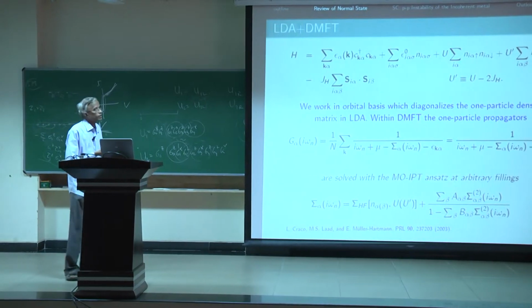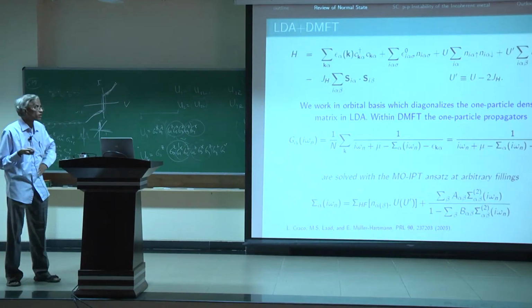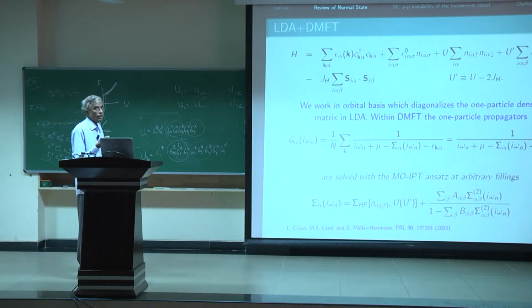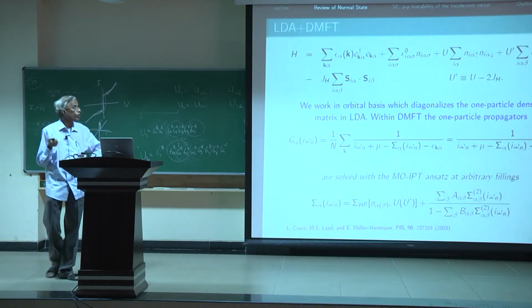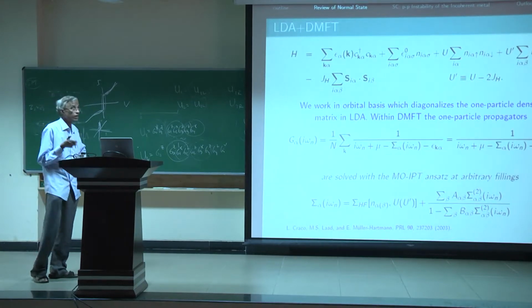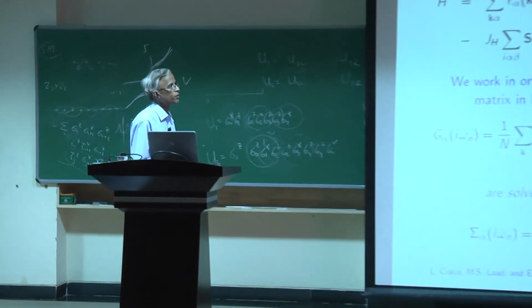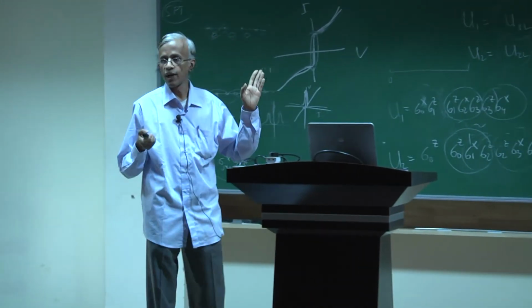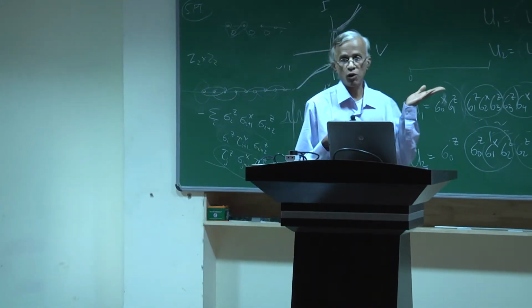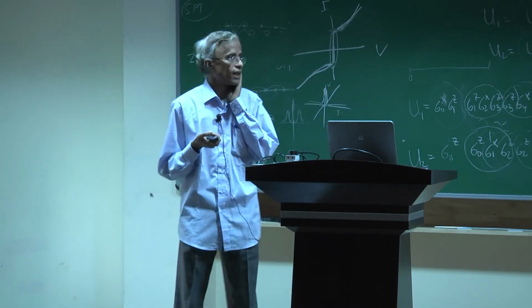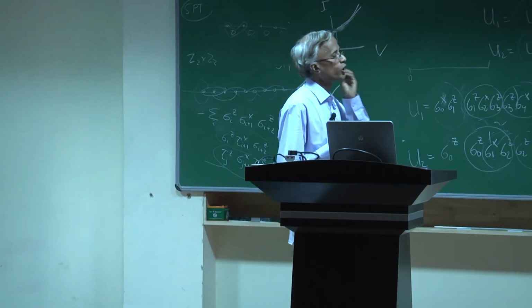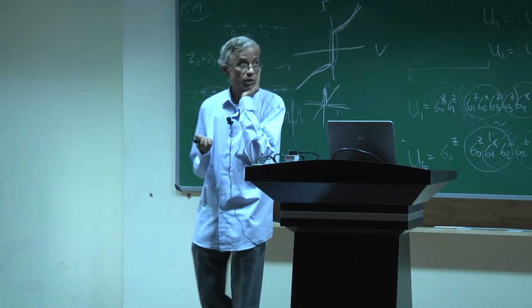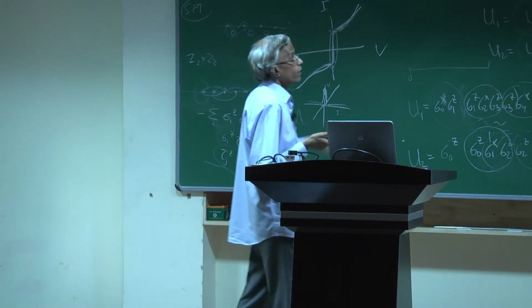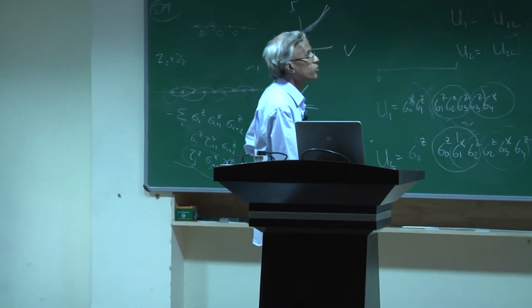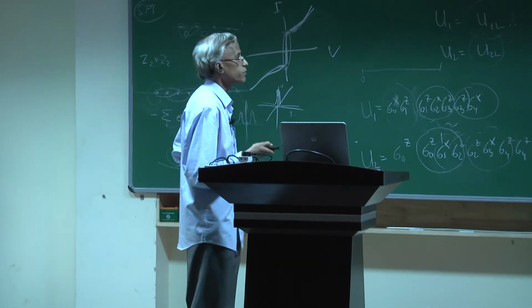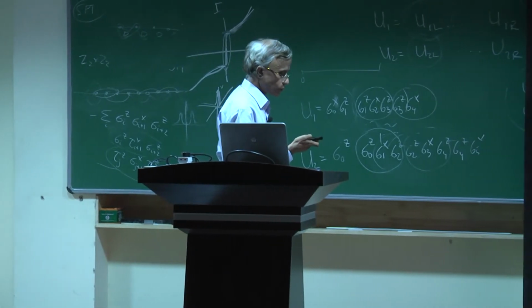But what that suggests is basically that an orbital order may preempt magnetic order, and if there is a ferroorbital order, it would induce a structural transition by coupling to appropriate symmetry adapted phonon modes. And indeed, in all the iron arsenides, you see that the structural transition always precedes the magnetic transition. And right, so that point of view was first taken by Philip Phillips, among others. And that's what I'm going to basically look at with the DMFT formulation.